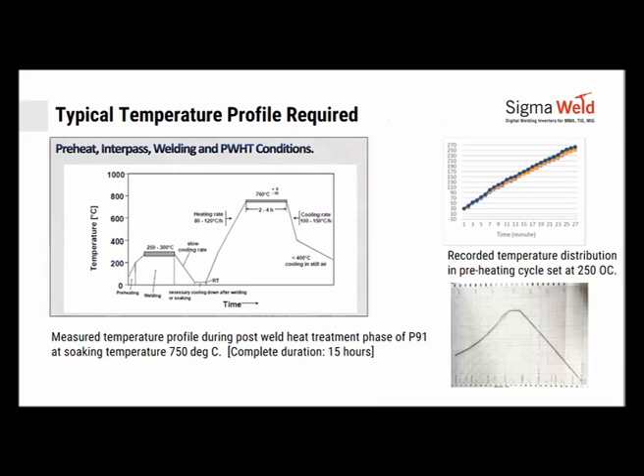Typical temperature profile required for preheating and post heating is something like this. Before you weld, you want to preheat the job. So you preheat up to 150, 200 degrees. During welding, you have to maintain the interpass under 250 or 300 degrees typically. And then you should have a slow cooling rate or necessary soaking for post heat for some time.